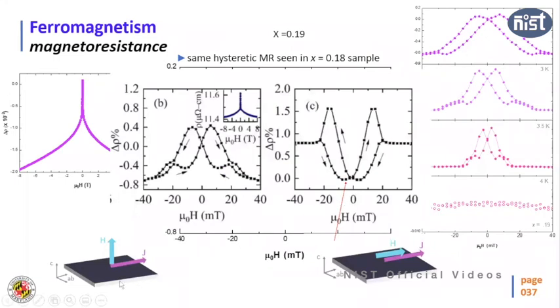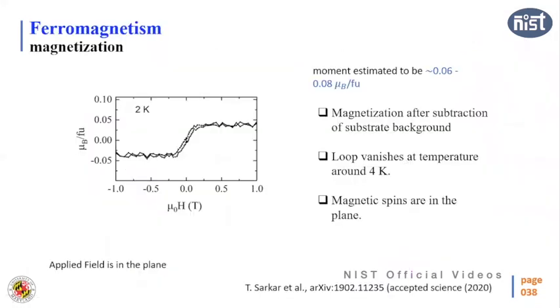Now, by the way, all these samples in which we are studying this ferromagnetism have no superconductivity. We are beyond the dome, so at low temperature we are studying. Now, what we found is that these loops are also anisotropic, meaning when you apply the magnetic field perpendicular to the current direction, it has this sort of loop. But if you switch the magnetic field direction and apply it parallel to the current direction, then it shows this kind of loop. Then we did a magnetization measurement.